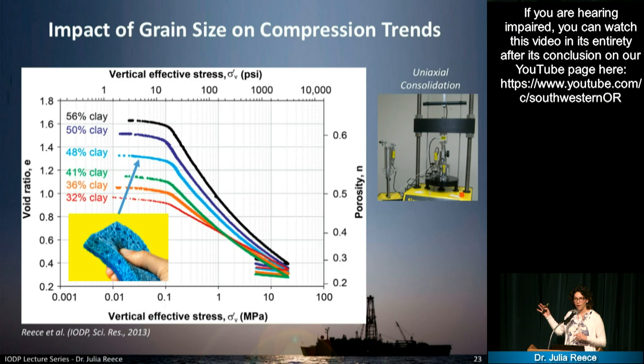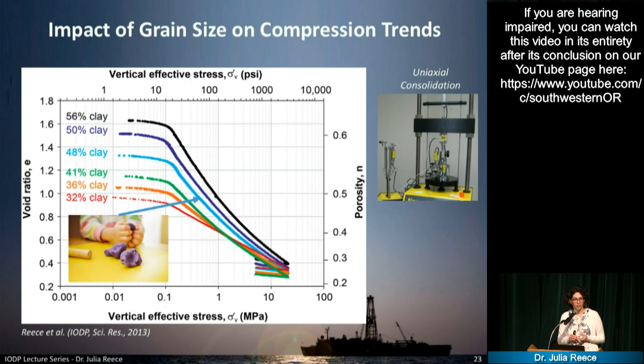So these fine-grained materials, these clays, actually have a memory. They remember the stress that they have been buried to in the past. And once they go past this stress, then they do not behave elastically anymore, but elastoplastically. And the best example would be Play-Doh. So if you push on some Play-Doh and you let go, it's not going to go back to its original shape. And so that's what's happening to these sediments. And in black, the pure Nankai clay has a much steeper slope, which means it is a lot more compressible or less stiff than the silt that is shown here now in red and not maroon anymore. Sorry.